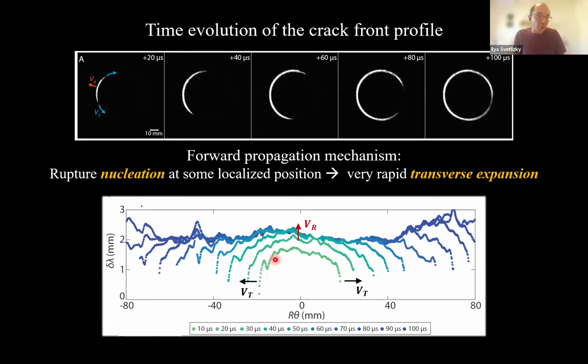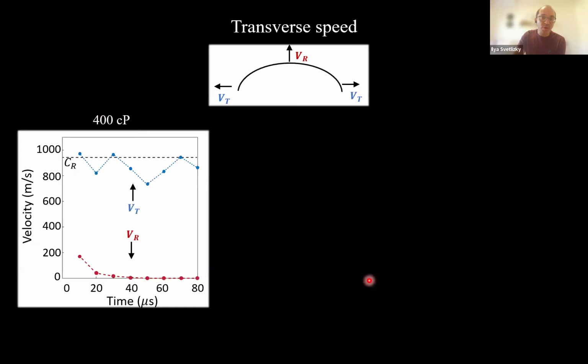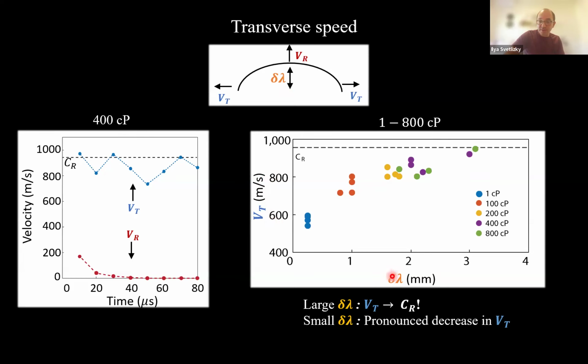So to quantify that, we can define two velocities. One is the radial expansion, VR, and the second one, VT, is the transverse velocity. So we track the velocities. This is the y-axis, x-axis is time. And what you see is that the transverse expansion is really, really fast, reaching the Rayleigh wave speed, whereas the radial expansion is really, really slow. It starts about 200 meters per second, but this is an underestimate because our time resolution is only 10 microseconds, right? But anyway, during most of the expansion of the crack, the radial velocity is really, really slow. And just to remind you, this is delta lambda, the jump amplitude. You plot the tangential velocity versus the jump amplitude.